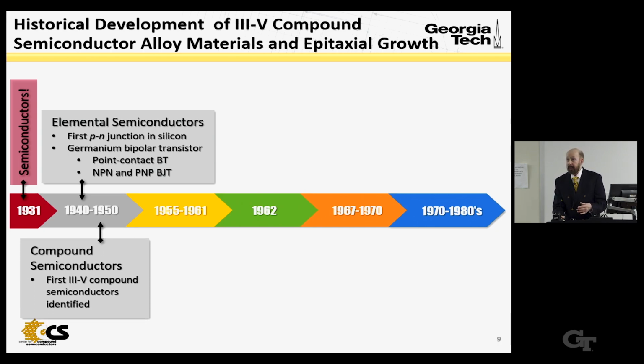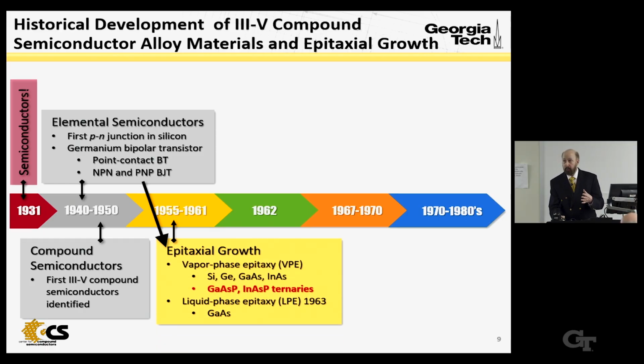1950 is the first announcement that 3-5 semiconductors exist. So this was basically work by Welker and Siemens in Germany, although others contributed to it. As I discussed earlier, the NPN and PNP transistor created the need for control of doping in 3 regions, the base, emitter, and collector. That led to the development of epitaxial growth, in particular vapor phase epitaxy first, for silicon, germanium, gallium arsenide, indium arsenide, and then the ternaries, gallium arsenide phosphide and indium arsenide phosphide. And a few years later, LPE for gallium arsenide, and a little later in 1967 for aluminum gallium arsenide.